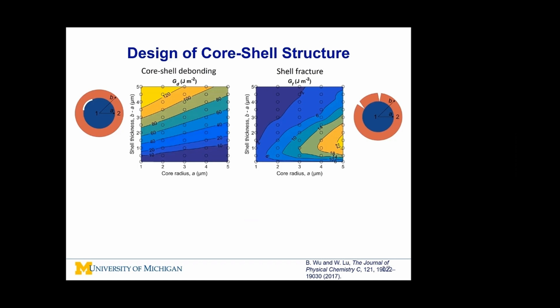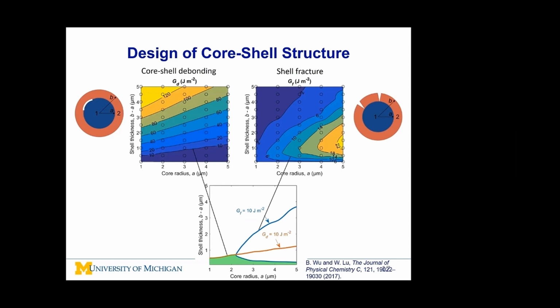The core-shell interface is prone to debonding for particles with a thick shell, while shell fracture is more likely to occur for particles with a large core and a relatively thin shell. Coupled mechanical electrochemical analysis allows us to generate a design map to avoid both failure modes.